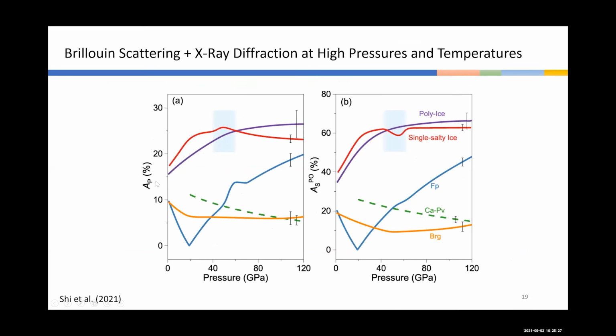Using this single crystal elasticity of solid ice, we also can calculate the maximum azimuthal anisotropy for VP, and also the shear wave splitting of this ice. We can compare with the lower mantle minerals. The interesting thing is that with increasing pressure, the anisotropy of the single crystal ice actually increases dramatically. There is also a softening behavior when it goes from ice VII to the dynamic disordered ice VII. There is a slight softening in the shear wave splitting when it goes across this transition. So this is one interesting thing.